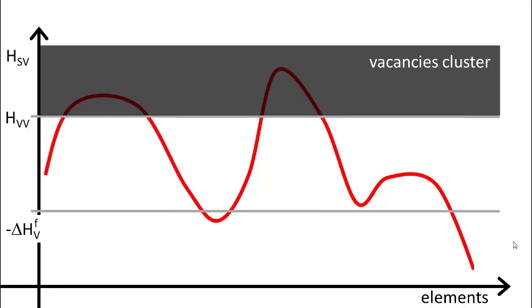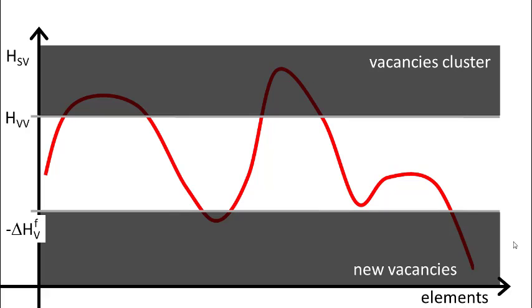Another boundary is set by the energy it needs to create a vacancy. So all these trapping enthalpies are negative, so if they are at the bottom of the scale, if they are maximally negative, a lot of energy is released when the vacancy gets trapped. And if that is more energy than you need to create a vacancy, then every trapping event will create new vacancies. So the trapping is not effective at all. So we should exclude also that region.